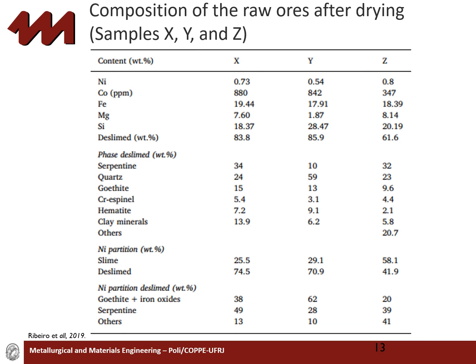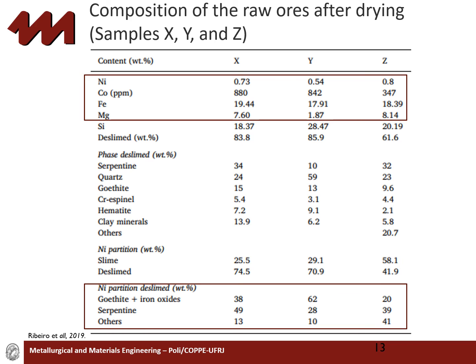For samples X, Y, and Z, nickel, cobalt, iron, magnesium, and silicon content, as well as nickel distribution in the main minerals, can be observed in the following table. Other minerals can be asbolane, tridymite, or amorphous phases. The characterization of the ore samples was carried out with delimed samples. However, for processing tests, samples were processed without disliming.